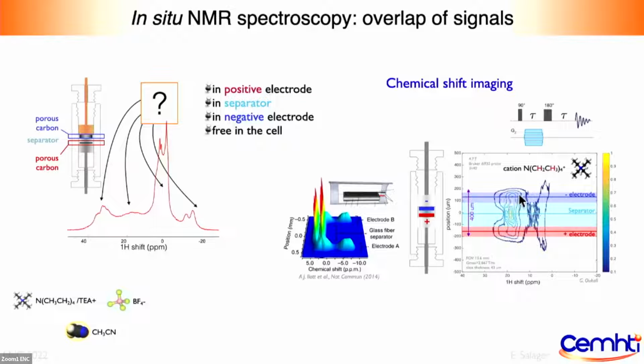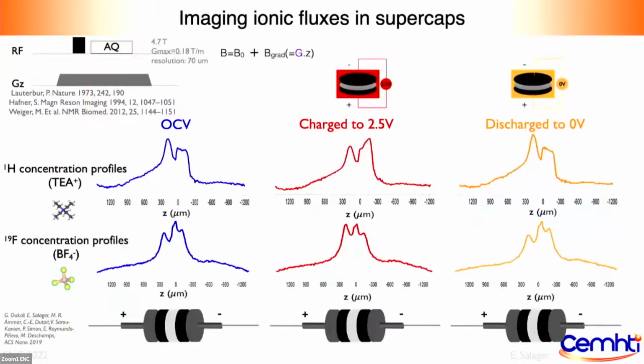And we do see shifted signals that correspond to relatively adsorbed cations and/or anions, but they actually don't change as we charge and discharge the battery. And this is because we're not quantitative. And the ISIS technique we used before for the batteries couldn't work here, mainly because the T1s are so long and we need to accumulate a lot of signal here. And so this would have taken too long. So what we decided to go for was pure imaging using ZTE